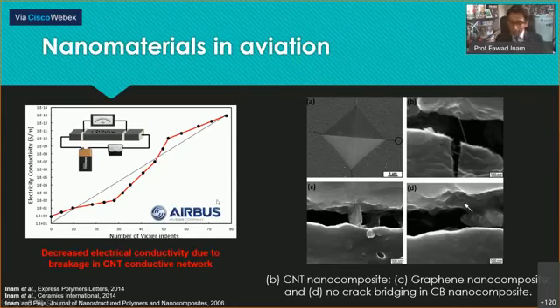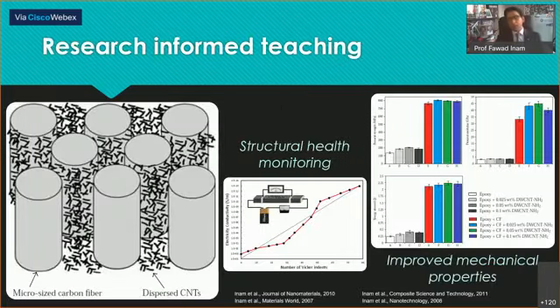So in this way, we started integrating what we call structural health monitoring. These, the big ones, are the micro-sized carbon fiber, and then we were dispersing carbon nanotube, which is the nanoform of carbon, and we realized that all of a sudden there's no need to have a metallic material, a material that is quite hard, for our soft and very brittle matrix. At the same time, we also observed that the material is responsible for some improvement in the properties.